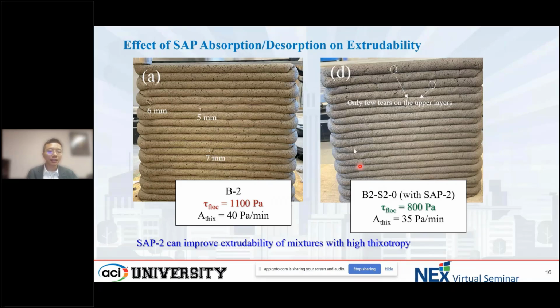And this is binder 2 with the very high flocculation value. So we can see the reference mixture made without SAP. There are many tears and open voids on the surface, even though these tears and open voids are small, not very big. But as we add SAP2, which can absorb water rapidly and also reduce the floc value, we got a beautiful surface, just with very few tears on the upper layers.